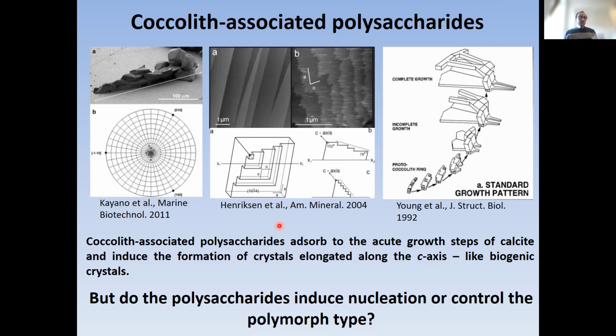And we know a little bit about what they do in terms of controlling morphology. It's been shown in the literature that they can promote the formation of crystals that are elongated in a way that resembles the single crystals in the coccoliths. So we can see here in this image, I have this crystal that instead of a rhombohedral crystal is very much elongated. And that is because it's making the crystals grow faster along the C-axis.